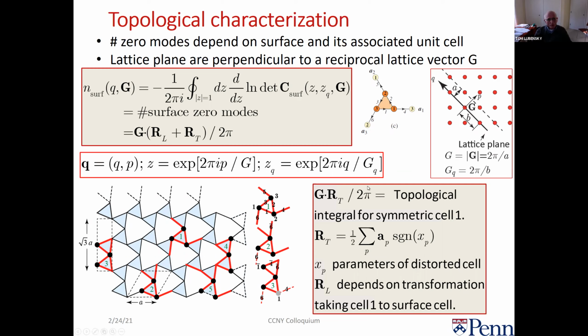And you can show then that this number, the number of surface modes, is the reciprocal lattice vector telling you what direction the surface is, dotted into a topological vector, the topological polarization R_T, plus a correction term, which is associated with the surface and how you've defined your unit cell.